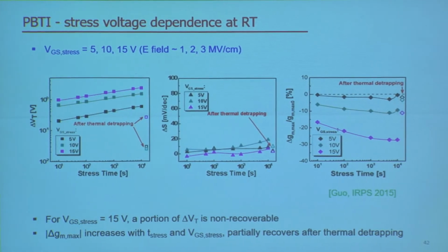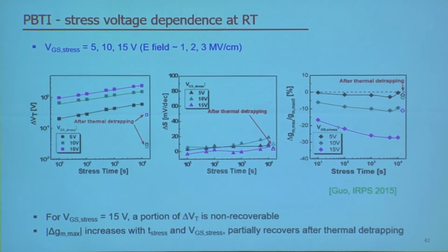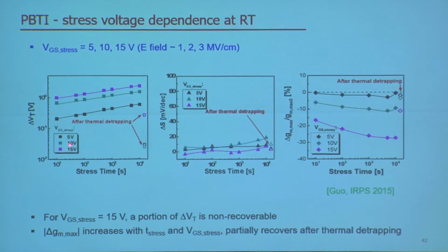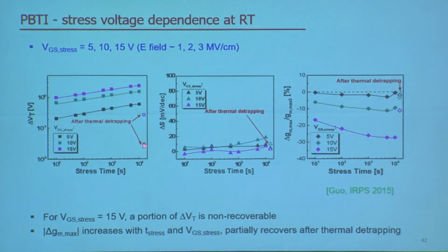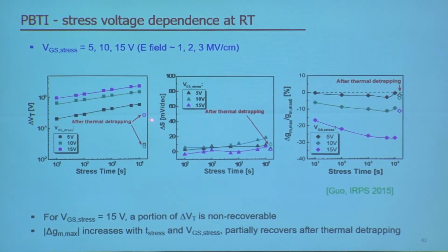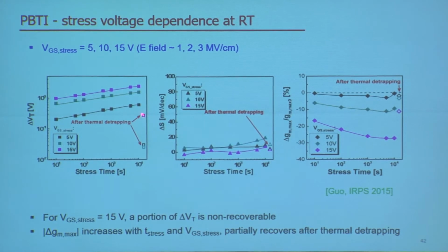What you see here is at room temperature, we stress the device at 5, 10, and 15 volts, and we want to focus on this leftover or permanent degradation at the end, where you see that there is a pretty large leftover positive VT shift after 15 volts of stress. And this is accompanied by a degradation of GM, but not so much subthreshold swing degradation.